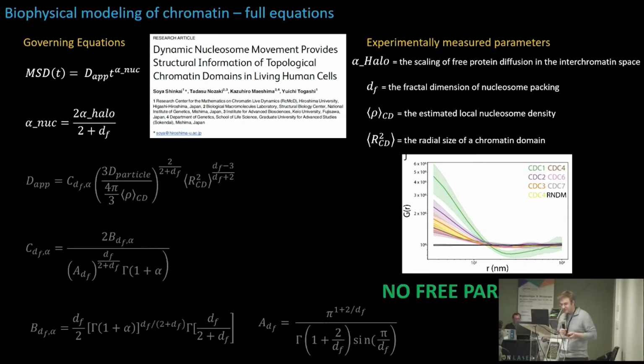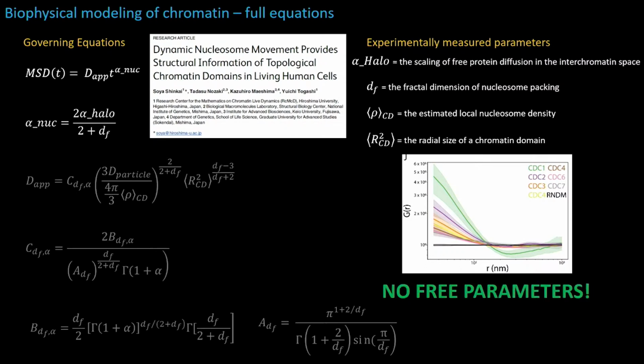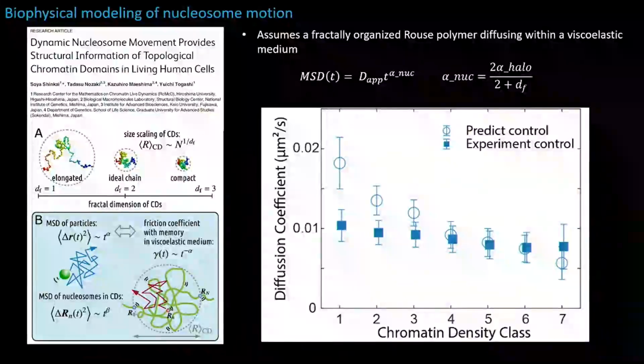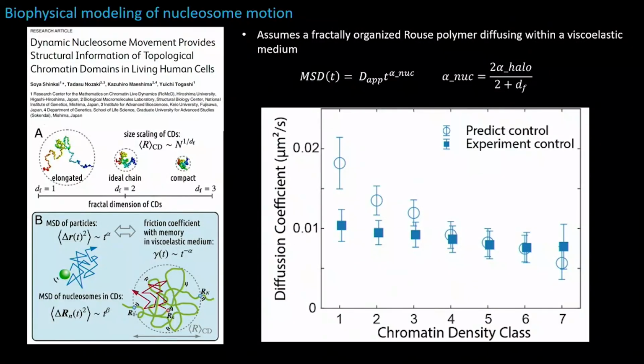So the unique thing about this that I think is quite interesting is that this is a bottom-up polymer model that has absolutely no free parameters to fit to our experimental data. Every parameter in the model is defined by experimental measurements in our system. And if we put this through our pipeline, we can use this now to predict what the apparent diffusion coefficient would be for nucleosomes in these different density chromatin environments. This is our experimental measurements in control cells, and this is what our polymer model would predict.